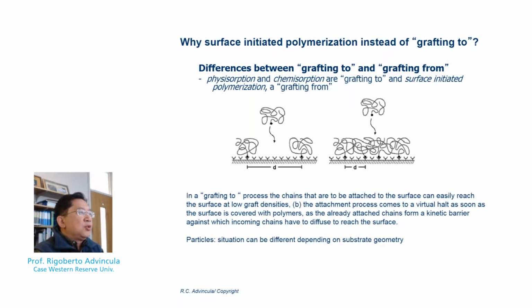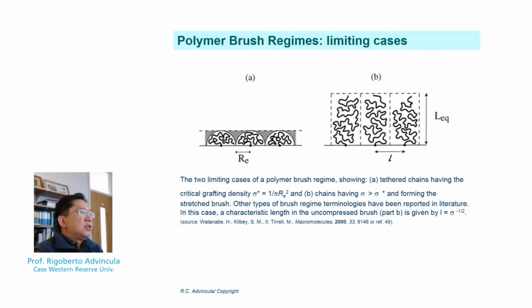Now, this typically shows you some differences from the grafting to or grafting from. In a grafting onto method, the polymer approaches from the bulk interface or solution, which can be achieved by physisorption or chemisorption method, of course. That means that the pre-existing polymer with its given molecular weight, polydispersity, and availability of the reactive group or physically absorbing group has to find its way to the interface. Hence, some of the challenges of a grafting onto or to approach is that of achieving a very high grafting density. And it is also, of course, related to the different regimes by which a polymer or a grafted polymer falls onto in its certain stages of equilibrium.